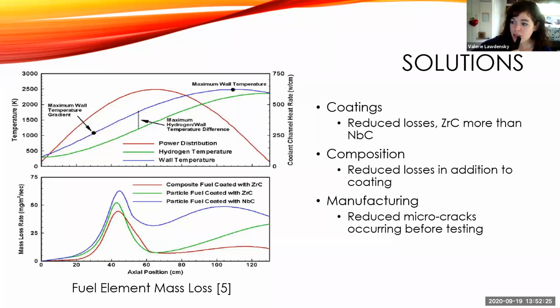The green is the zirconium, and the red is that composite matrix. They also found that the coefficient of thermal expansion was a huge, huge factor in this, because the coating had about a 7.6 compared to the fuel elements at a 6. That was why we were seeing some micro cracking, because the location where these serious mass losses occurred, which is called the midband region, actually coincides with the temperature range in which the coating is applied.